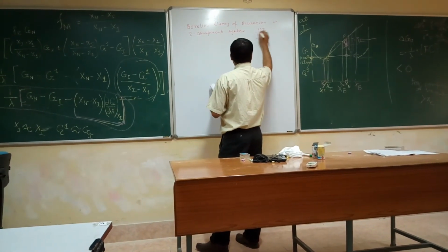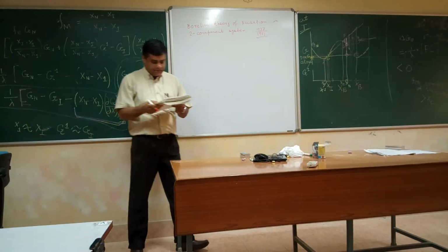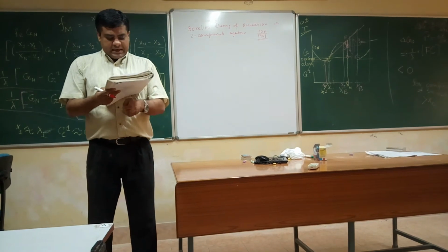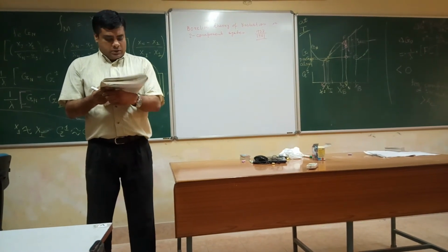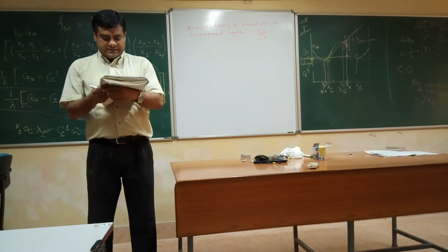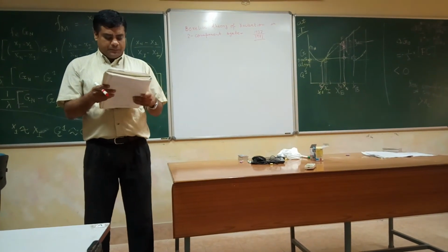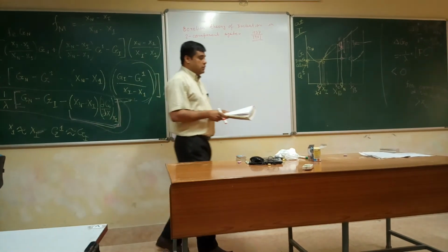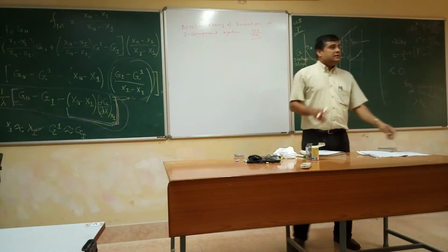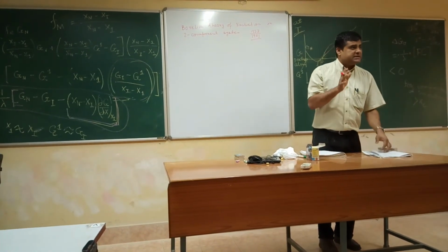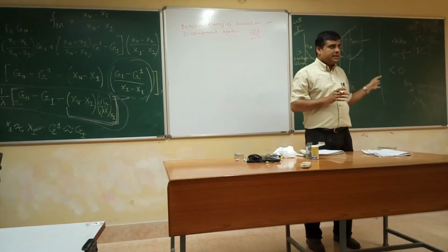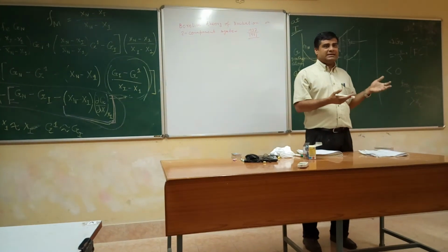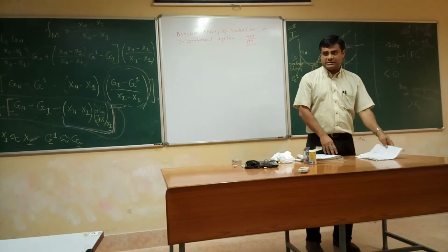There were two papers published in 1937 and in 1951 where the basic assumption of this model was that a group of atoms of fixed size achieve stability by fluctuations in composition. So what Becker did, he assumed composition is fixed at x beta. Then he used the classical nucleation theory to find out the critical size of the nucleus.